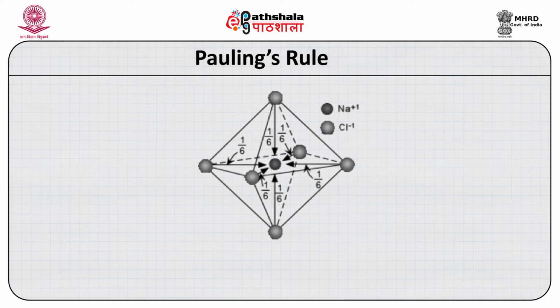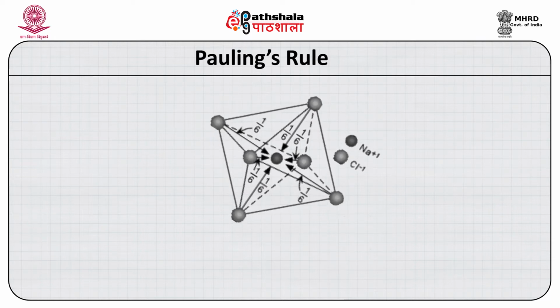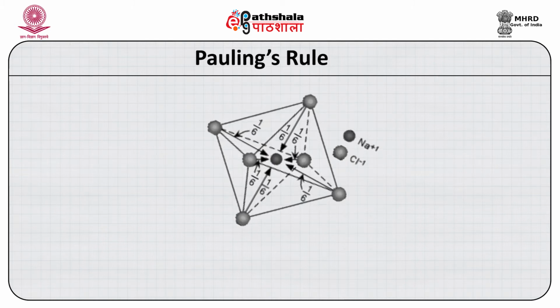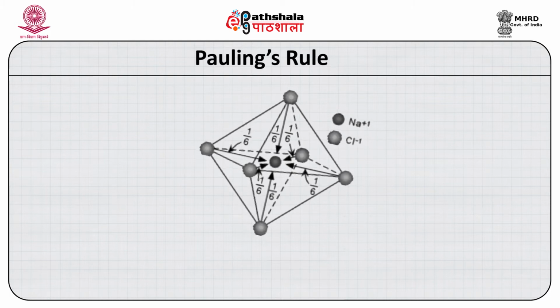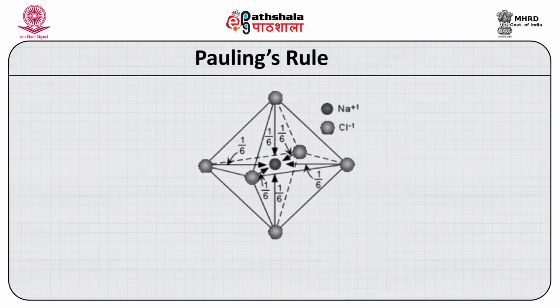Let us say in the case of carbonate structural groups like CO3, the C4+ ion is in triangular coordination with oxygen, and here the electrostatic valence works out to 4/3, that is, C has a charge of 4 and a coordination number of 3. Thus, 3 oxygens contribute 4/3 charge to the carbon ion, and the charge on the carbon ion is balanced, but each oxygen still has 2/3 of a charge that is unused, which leads to formation of bonds with other elements, and therefore, this is an example of anisodesmic bonds.